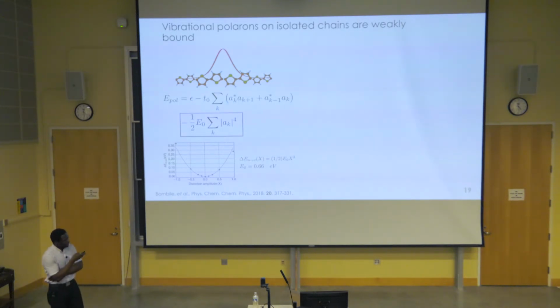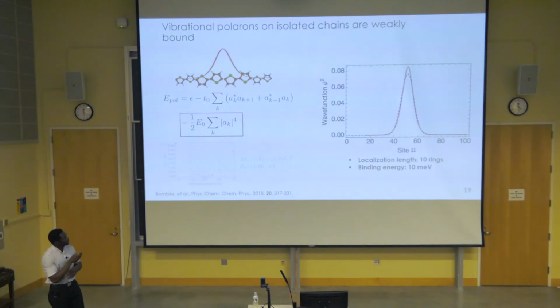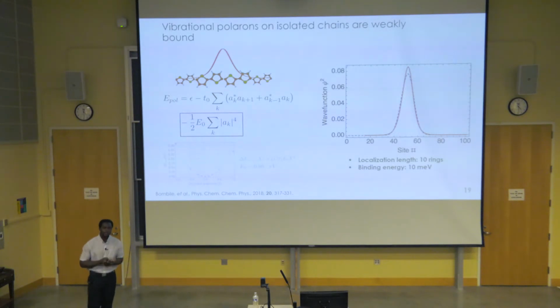Through the competition of these two terms, we have an optimal size of the polaron that will arise, and particularly we found that polarons that occur through this mechanism are localized over just about 10 rings with a binding energy of 10 meV, which is rather small in comparison to the thermal energy at room temperature of around 25 meV.